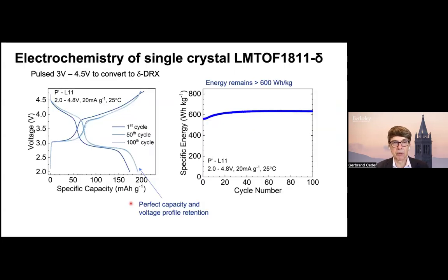So these materials work extremely well. This is after the formation cycles, where pulsing has been done. Here you see a discharge curve. This is the first cycle. There's still a bit of remnant transformation. By the 50th cycle, the capacity is larger, but there are actually two lines here, which are the 50th and the 100th cycle. These are exactly on top of each other, so there's virtually no degradation at all in this material.